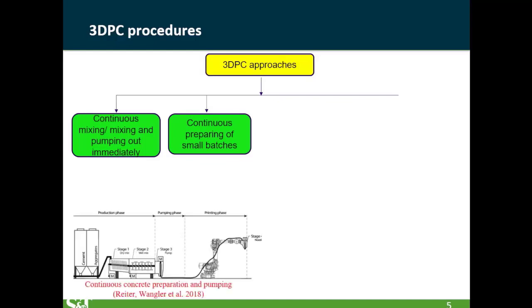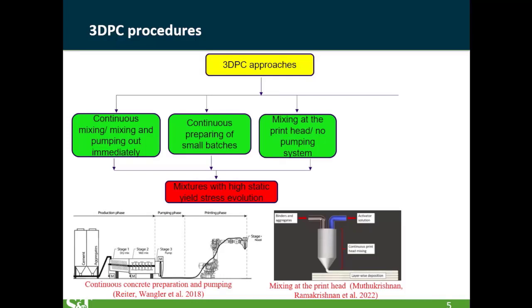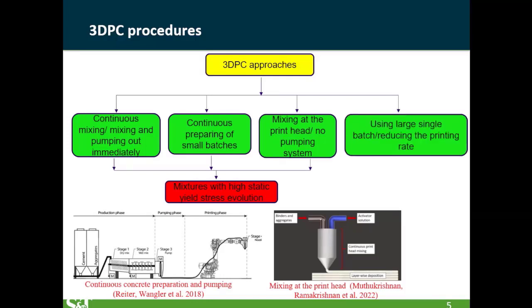In this study, we started looking at the different procedures available in the literature for 3D printing. One approach is continuous mixing, where you do the mixing and pumping at the same time, or you can have continuous preparation of small batches, and once you prepare the batch, you start pumping. Or you can have mixing at the nozzle head. The other one is to use a large single batch. Those are basically the four methods that we found in the literature for 3D printing. The objective of our study is to prepare different mixtures that can be used for different procedures. So we are looking at optimizing different mixtures for different procedures.